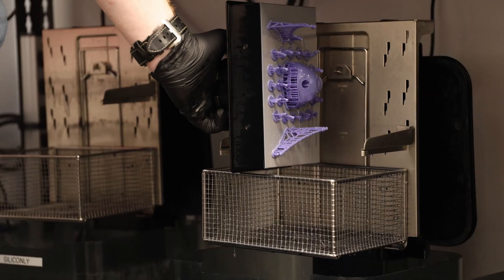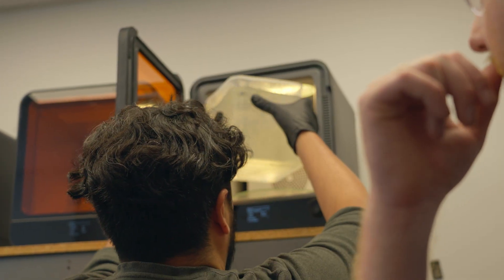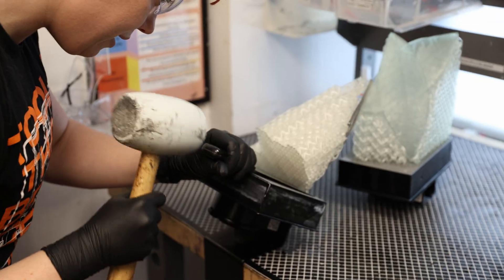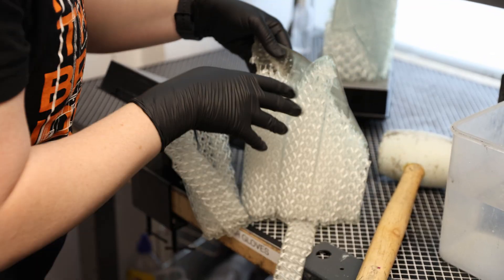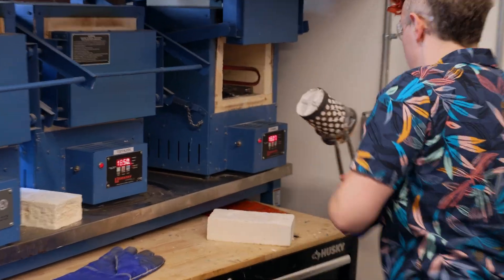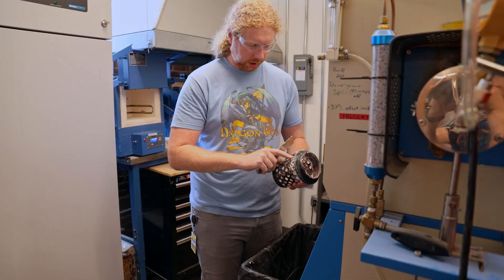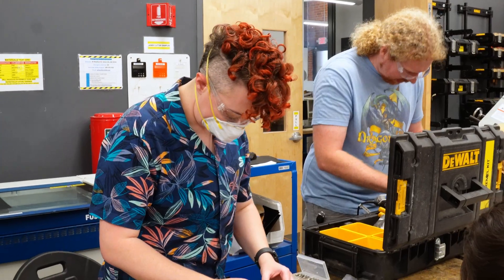The clear leaves are actually a flexible resin that need to be supported all over or they will warp horribly in the printing process. The strange purple beetle pieces are actually two different types of wax resin — one better for tiny details in delicate pieces and one easier to cast with. Like with all resin-based printing, we still need to wash off uncured resin and then bake them in a UV oven so they reach maximum strength and can be safely handled. They also need to be painstakingly removed from the build platform, and as a team it was a lot more manageable.